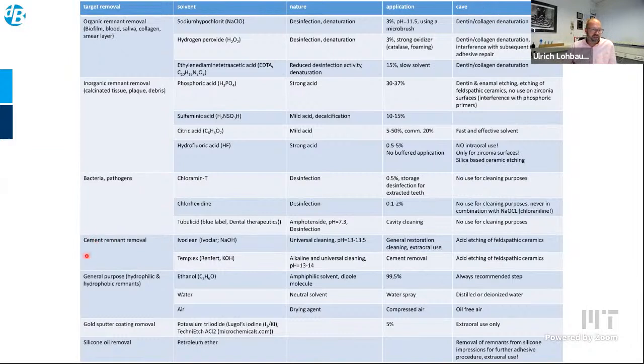At some point, in our case, we fix our restorations with cements, water-based cements or adhesive cements. We can remove them with alkaline cleaning solutions. Then we have the typical cleaning solutions that the dental practitioner uses in dentistry, like water and air, ethanol, which is not critical intraorally. We have some others like silicone oil removal that is necessary when we are using silicones for impressions in the mouth. So we also probably have contamination of surfaces with silicone oil. All right, so cleaning is one thing that is really necessary before any inspection of a surface.